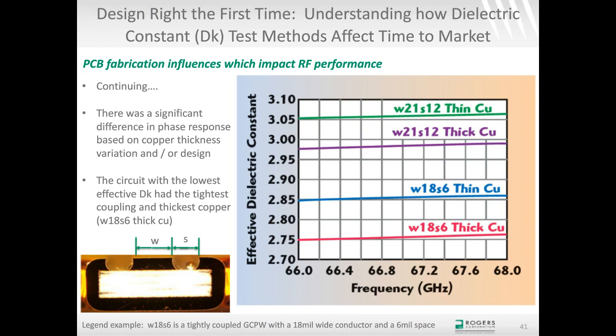the effective dielectric constant on the y-axis, frequency on the x-axis. And here I see a little difference, and it's pretty interesting. The circuit with the lowest effective dielectric constant was the circuit with the tightest spacing, which means it's tightly coupled, and that means there's very strong electric fields between the signal conductor and the neighboring ground, and also the thickest copper. My opinion is when it's very tightly coupled, the electric fields are using the air very efficiently. Being thick copper, these sidewalls are much taller, so again, you're using air more efficiently. Air is the lowest dielectric constant, it's 1, so that lowers the circuit effective dielectric constant, and that's why the red curve is the lowest effective dielectric constant.